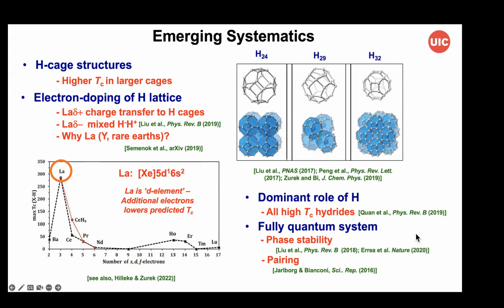So these are very much high TC hydrides in the spirit of metallic hydrogen. This is a point that Warren Pickett has made in a number of papers. But another important point is, even though the electron-phonon coupling seems largely responsible as in conventional superconductors, the fully quantum system affects the phase stability, and in more detail likely affects the pairing in the system, which is neglected in these more or less routine calculations that are being done now. So there's a need to extend the theory to make this a fully quantum system. I'll come back to this point at the very end of this talk.